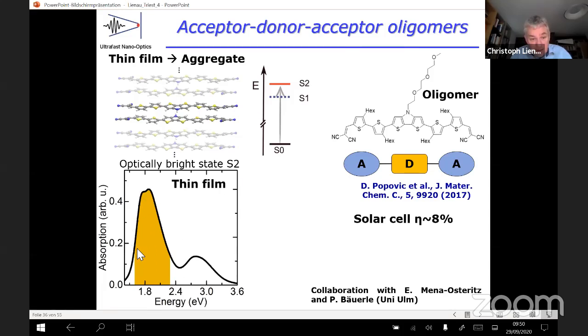looks very simple. There's a broad peak around 1.8 electron volts, and we probe this now with very short pulses with a spectrum that basically is marked in orange here. Again, this is a typical solar cell material. The chemists say this charge transfer is good to make this an efficient solar cell material. Efficiencies at the moment are on the order of 8% here, and it's nice and stable, has a broad absorption spectrum, but one does not understand why it works. That's pretty much similar to the P3HT PCBM case.